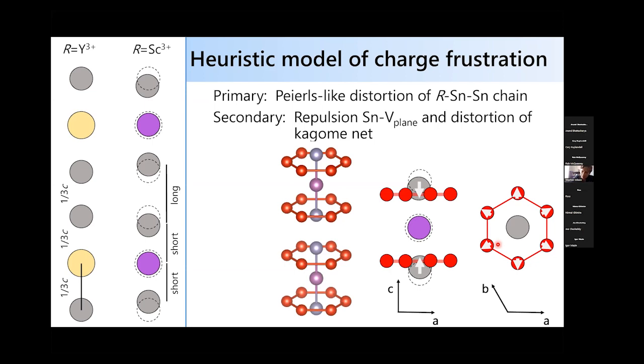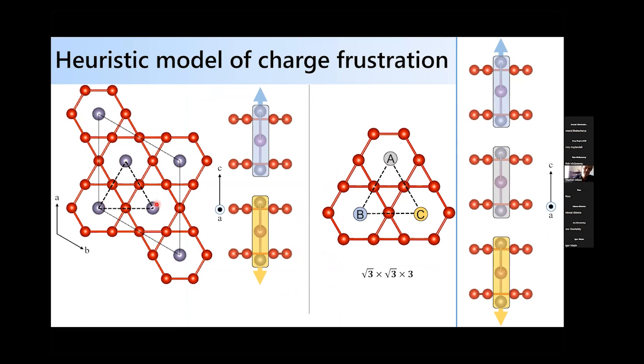Okay, so fine. If I build out one more level in terms of the in-plane structure, you have these chains going through the centers of these hexagons. And since there's a steric penalty for moving one tin atom into the vanadium plane, you don't want to put two trimers moving in the same direction next to each other. So then you can imagine I have a triangular lattice, where I have to try to decorate one trimer moving up next to one trimer moving down. So what you end up with is a frustrated lattice in this regard. One way the system can solve this is to unlock an additional degree of freedom along the chain: one trimer moves up, one moves down, and one doesn't move at all. And so then you have an ABC tiling of this triangular lattice.